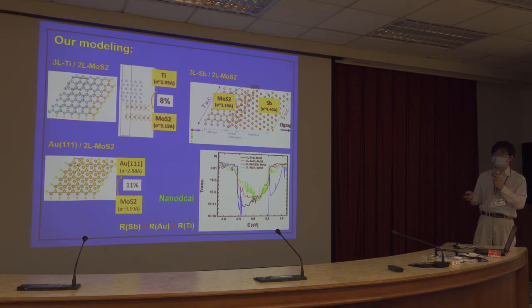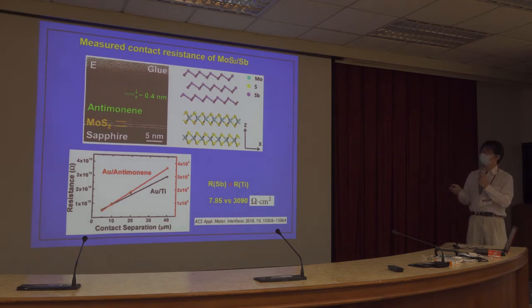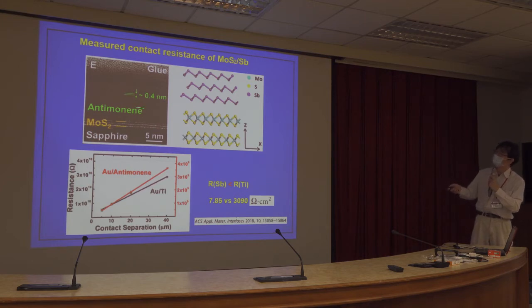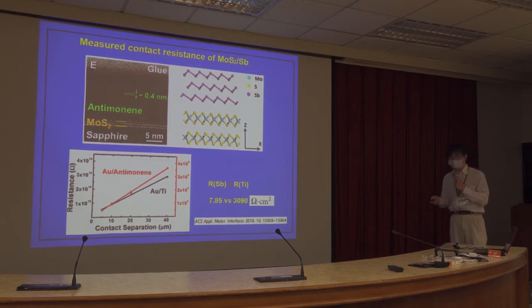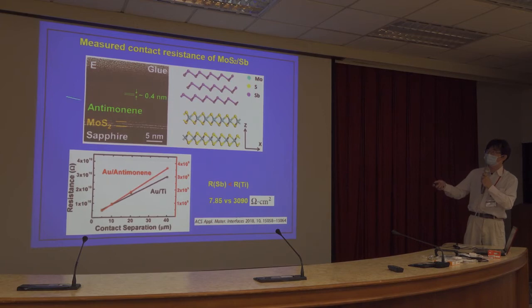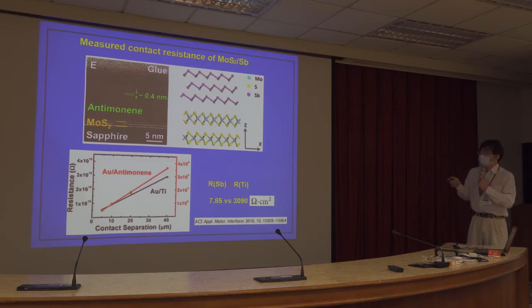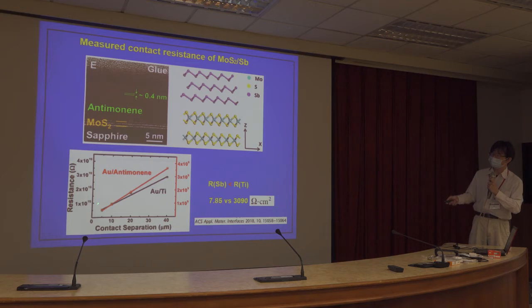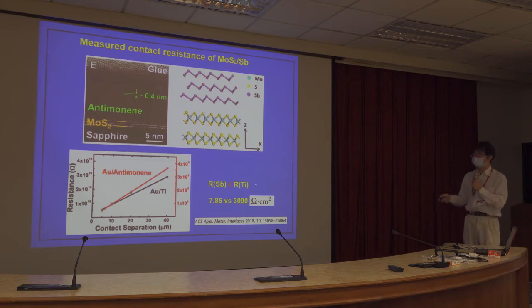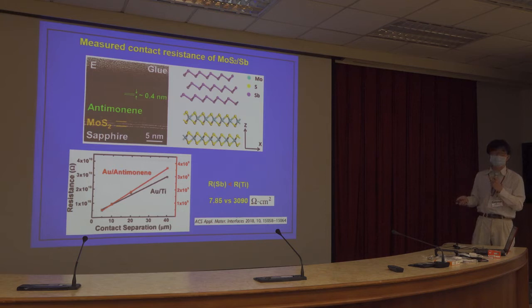The results show: green is Sb, red is gold, black is Ti. Our conclusion is that Ti contact resistance is indeed greater than gold, which is greater than Sb. Our calculation suggests Sb may be a material providing smaller contact resistance. Our collaborator's experimental group fabricated this system, showing Sb has a layered structure with MoS2. Experimentally, the extracted contact resistance shows Ti is above Sb, confirming Ti contact resistance is greater than Sb — dropping from ~3090 to ~7.85 Ω·cm2.